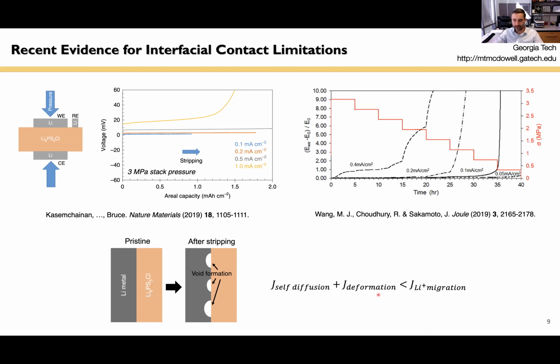And the basic theory here is that as you're stripping lithium from the interface, the rate of the flux due to self-diffusion of lithium from the underlying lithium metal, as well as the mechanical deformation of lithium, both of these have to be, if they're less than the rate at which you're stripping lithium, then you're going to form voids. Nothing you can do about it. So it's a fairly simple idea. But we wanted to investigate this in more detail to understand how prevalent this void formation was, and to see if we could image it.